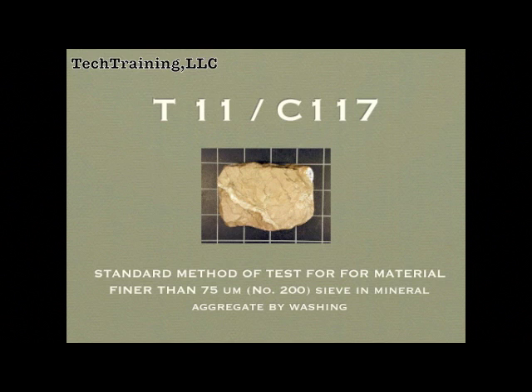If there are an excessive amount of fine particles, inadequate bond between the hardened cement paste and the concrete aggregates will result. This can cause low compressive strength, reduced durability, and in some cases pop-outs where the dust-coated particles exist near the concrete surface.